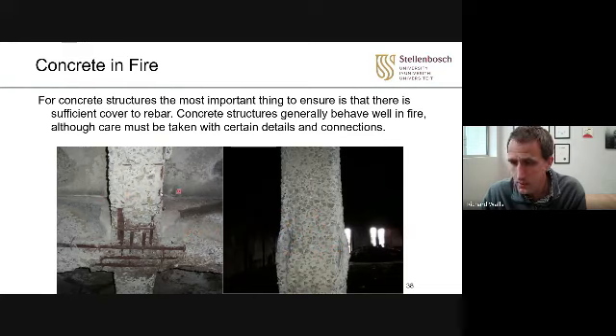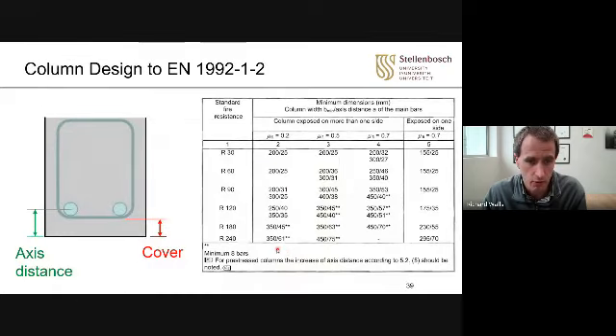So this is pretty complex. There's very, very little strength left. This is a problem. You don't want to put big machines in there to demolish it. You've got to be careful. So this is when the fire's been very severe for a very long time. This fire lasted many hours. That was the problem. It was beyond what the building was designed for. One of the useful things with fire design, especially with our local codes, and you'll probably find it similar with your codes, is often structural engineers focus on what's called cover. So cover is the distance between the outside of the concrete and the first piece of steel.